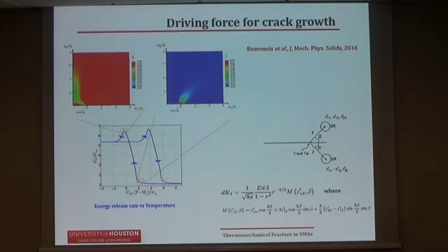And then we see this drastic increase in the energy release rate, in the driving force for crack growth. And this is due to the fact that most of the transformation happens in front of the crack. Because at the regions behind the crack, the stresses are low, so we need to cool further in order for those regions to phase transform. Then we reach a peak, and then this drop in the driving force for crack growth is due to the fact that now the regions behind the crack tip start transforming, and they induce those compressive stresses that tend to close the crack. Right? Once the phase transformation is completed, nothing happens.